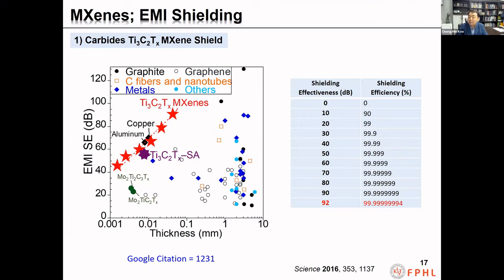So huge, yeah, so outstanding shielding performance is attributed to high electrical conductivity, as well as layered laminate structure of micrometer thick MXene films. Additionally, the abundance of the surface termination group can induce strong dielectric polarization loss that may also contribute to the outstanding shielding performance. Now, this paper is one of a highly cited paper.